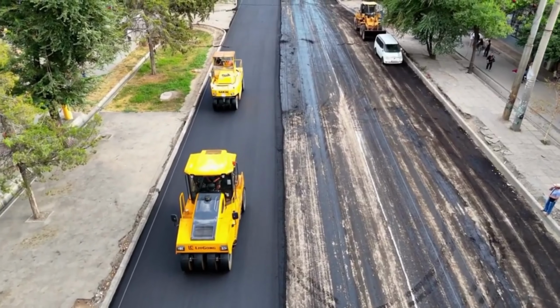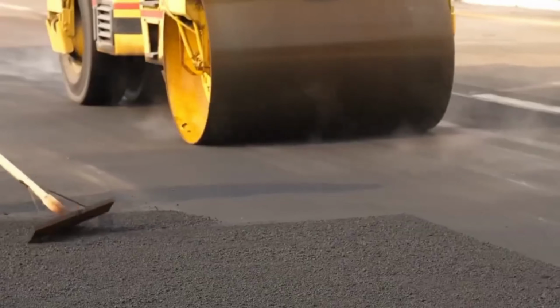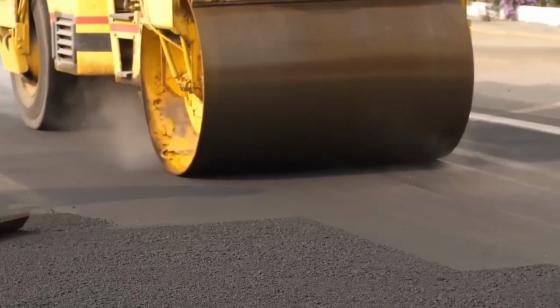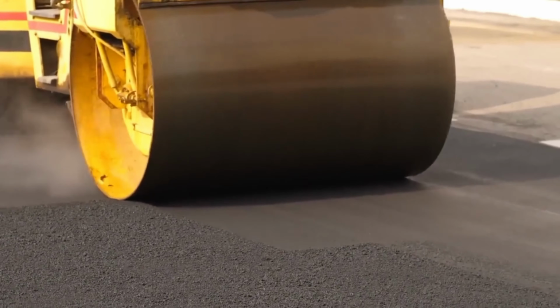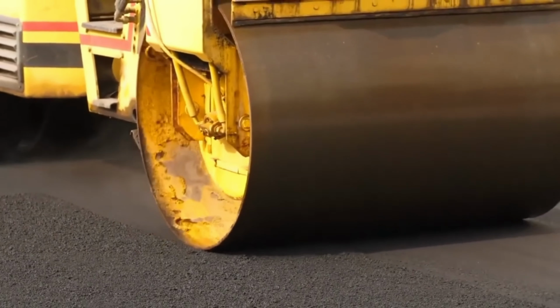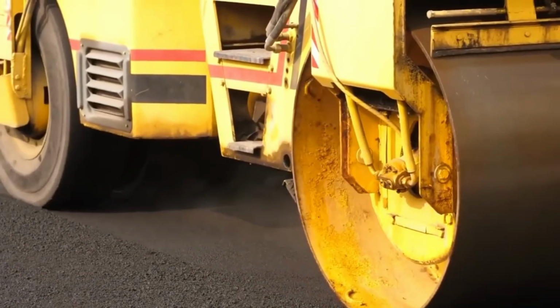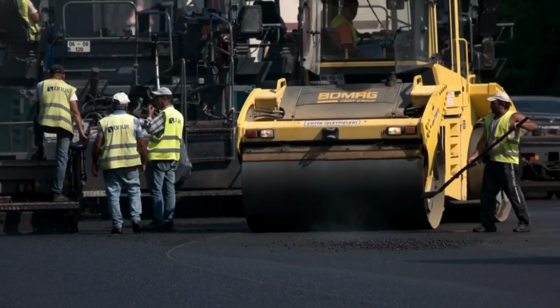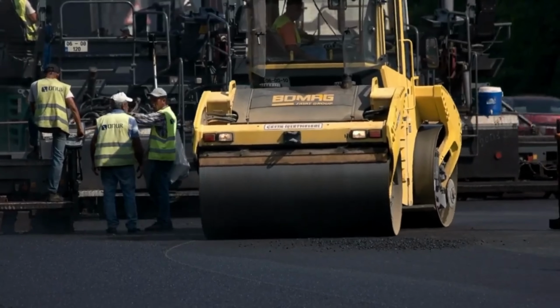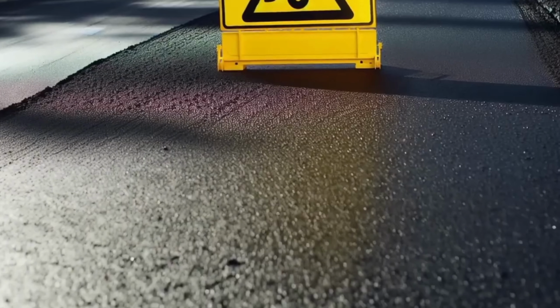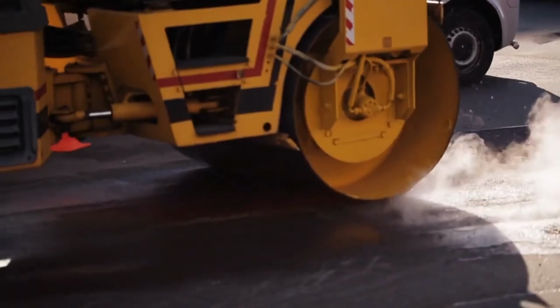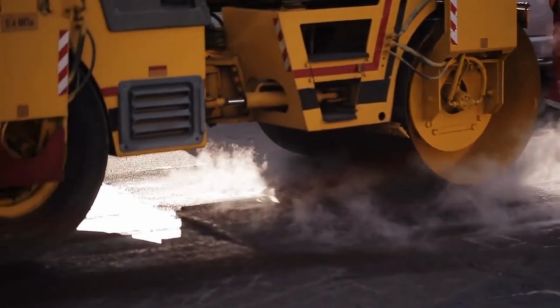Compaction is where asphalt gains its strength. Steel drum rollers and pneumatic tire rollers make multiple passes to squeeze air voids from the material and lock aggregates tightly together. The exact number of passes depends on temperature, roller weight, mix design, and mat thickness. Rolling patterns are calculated precisely.